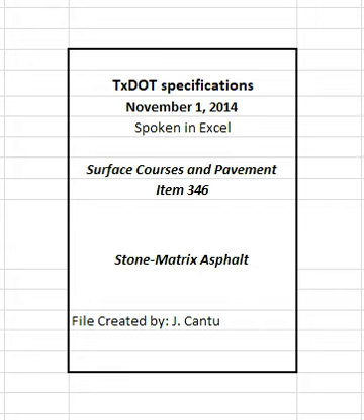4.9.2.4.2 Asphalt binder content. A sublot is defined as out of operational tolerance if either the engineer's or the contractor's test results exceed the values listed in Table 9. No production or placement payment adjustments greater than 1.000 will be paid for any sublot that is out of operational tolerance for asphalt binder content. Suspend production and shipment of the mixture if the engineer's or the contractor's asphalt binder content deviates from the current JMF by more than 0.5% for any sublot.